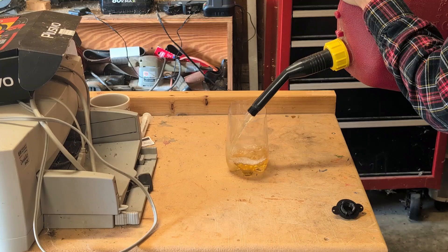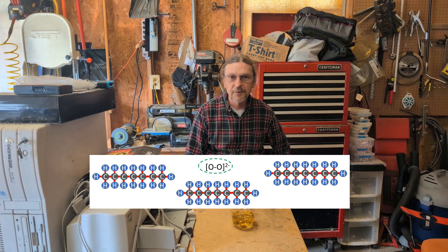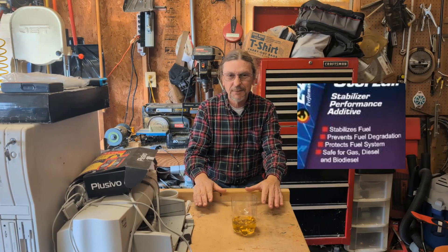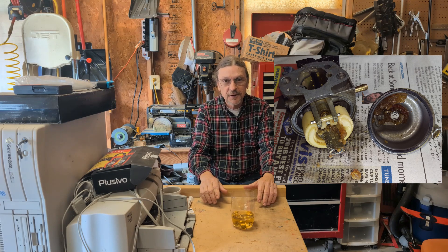This is the gasoline I pulled out of my motorcycle a few videos back — it's over a year old. The third way it goes bad is polymerization. Notice that this gasoline is turning brown. Polymerization is short-chain hydrocarbons linking together to form long-chain hydrocarbons — in fact, this is how plastics are made out of petroleum products, and also how a furniture oil finish will cure. The second type of stabilizer tries to reduce this, but it has its limits. This is the carburetor from that same generator stored for almost three years — that chunky brown stuff is not the additives; that's the actual gasoline itself polymerizing into lacquer, varnish, gunk.